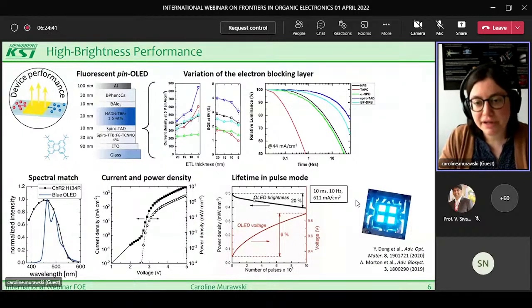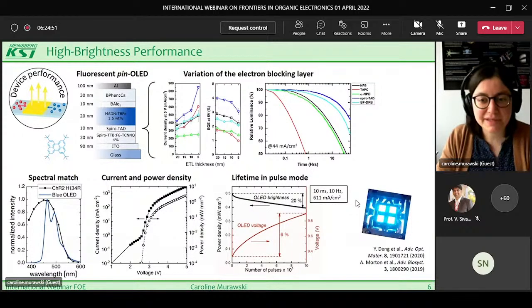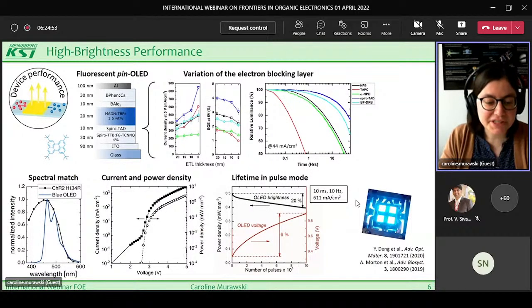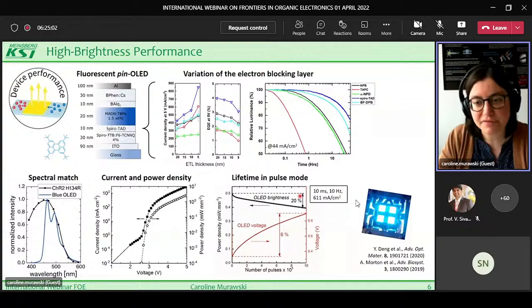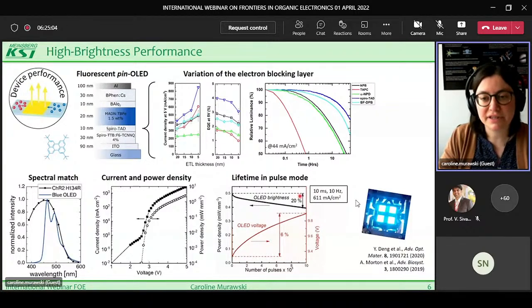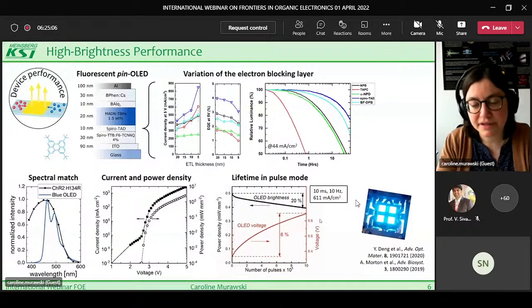Over this driving course of 1 million pulses, we have a decrease of OLED brightness of around 20%, which I think is acceptable, and which is also at least supporting the fact of using fluorescent emitters, especially for the blue. I believe with phosphorescent and TADF emitters, this brightness drop would be significantly stronger.